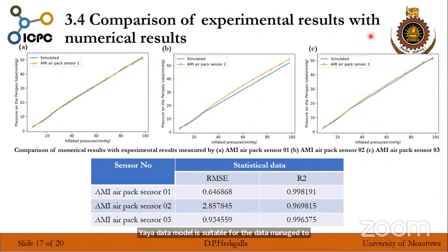And this is the comparison of experimental results with the numerical results. As you can see here, simulation results had more than 95% agreement with the experimental one. Hence, we have used this model to determine the pressure transmission patterns with different size and thickness.